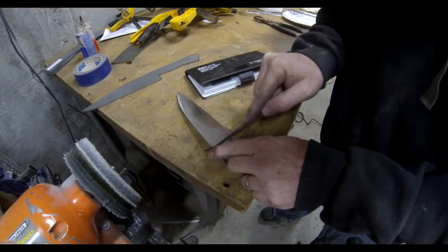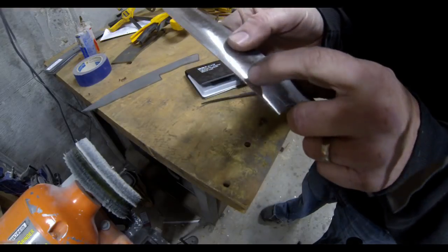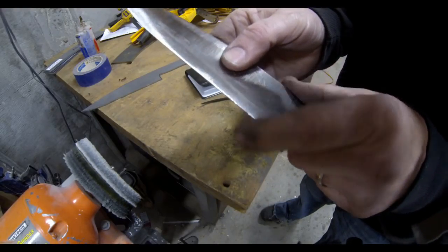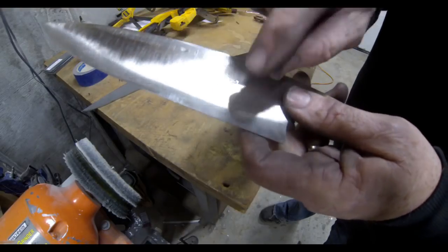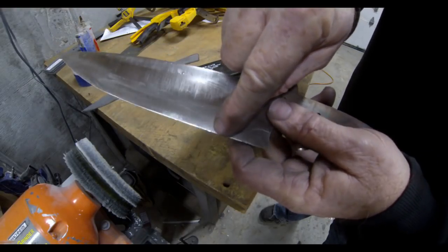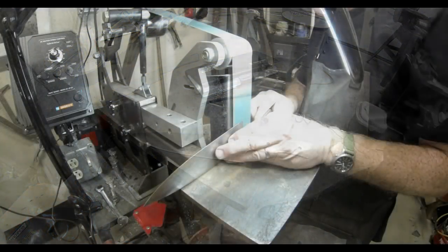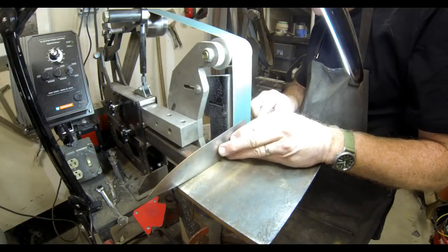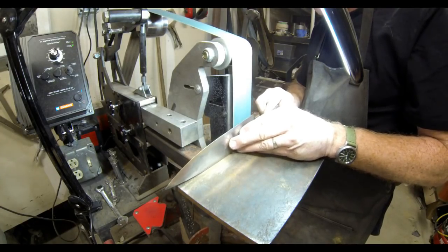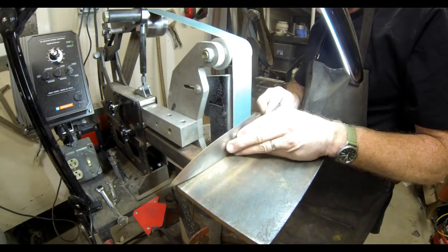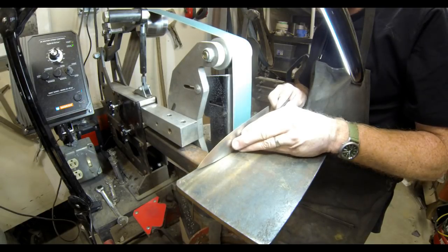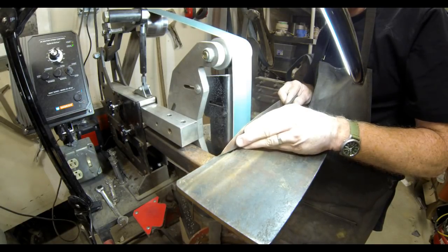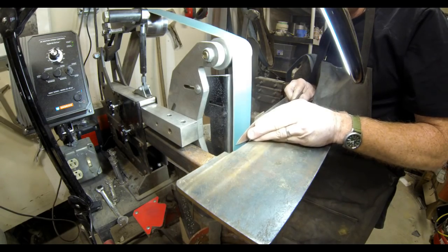I use Rockwell hardness files, just a very simple way of testing the hardness on a blade. And I was very pleased to find out that these blades, the AEB-L stainless, hardened right up to about 61 on the Rockwell C scale. So after I confirmed the knife was hard enough, I'm back onto the grinder and I'm using a finer belt. I went to an 80, and then I went to a 120.